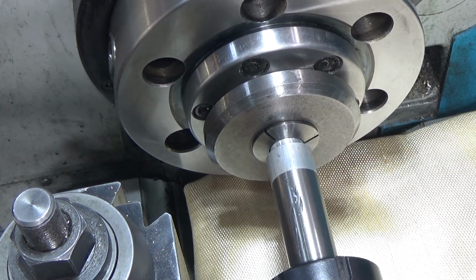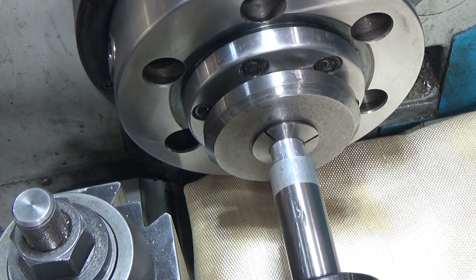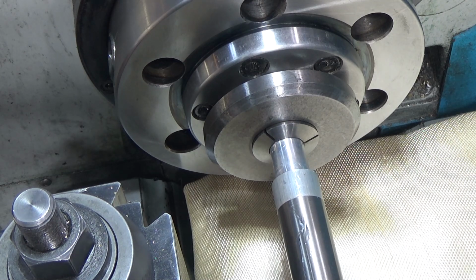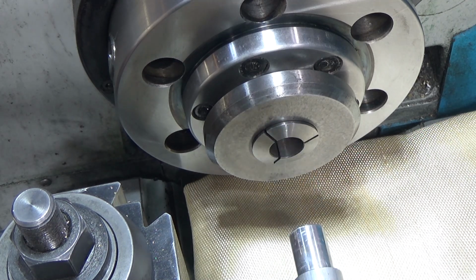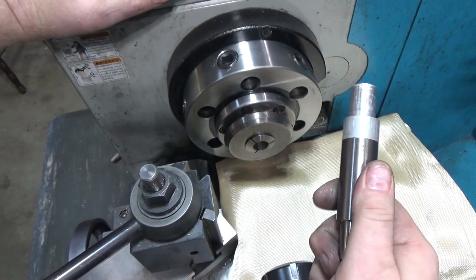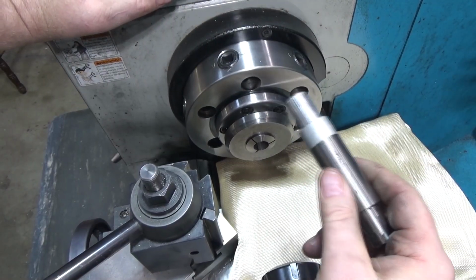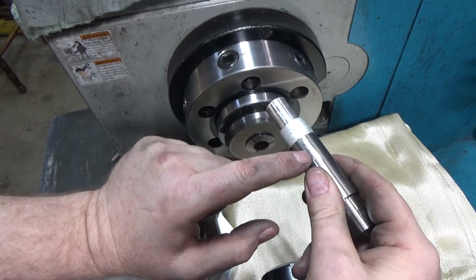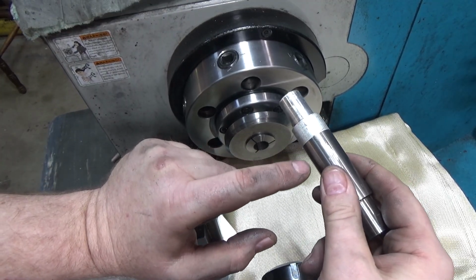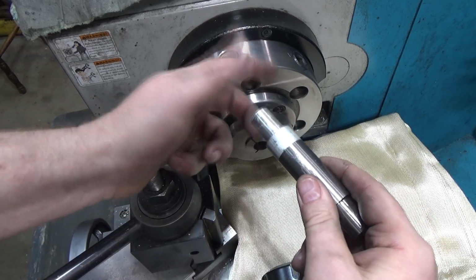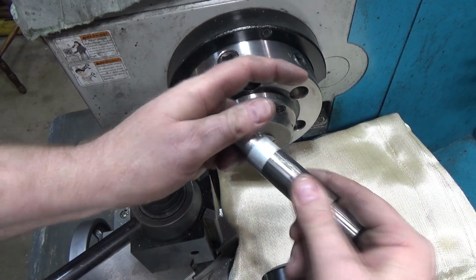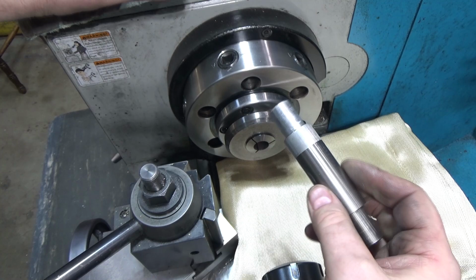Well, let's see, did we? Hey, look at that. Looks like we got welding again. So I'm having much better luck with titanium and aluminum than I did with brass in any case. I'm really surprised by the titanium and aluminum, because the titanium has a much, much higher melting point than aluminum. So I'm surprised.